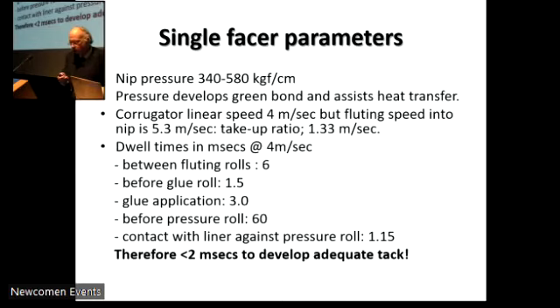But most crucially, we should look at the dwell times in this thing. If you look at it in milliseconds, at 4 meters a second, the dwell time between the fluting rolls is 6 milliseconds. Before the glue roll, where the glue is applied to the flute tips, 1.5. Glue application contact time, 3 milliseconds. And before the pressure roll, where we're forcing the fluting against the inner liner, 60 milliseconds. And the contact time with the liner as it goes through the pressure roll, in other words, the pressure pulse duration, is 1.15 milliseconds. So you've only got 2 milliseconds to persuade a relatively runny starch-based adhesive to make a bond that's strong enough to hold the board together through the rest of the manufacturing process.